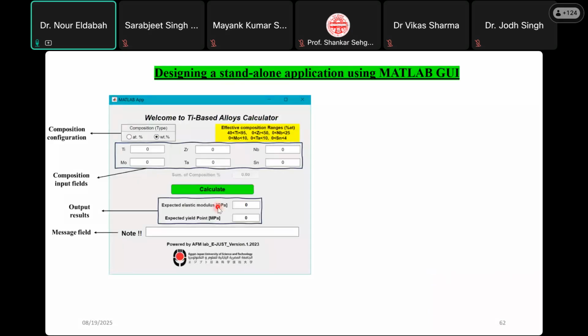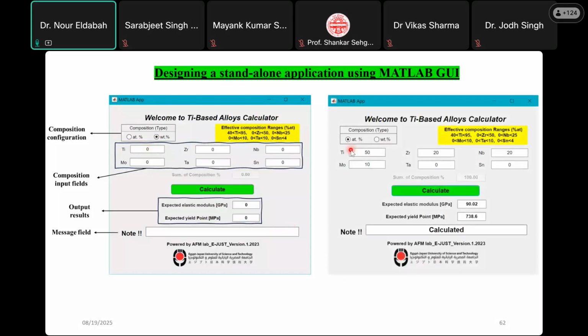Finally, to make our work effectively working, or accessible for all users, you can take your code and make a standalone application. In this standalone application, you can feed in your chemical composition, and it can calculate for you the expected elastic modulus and expected yield point. Actually, I built this application after the first case study, and it was very beneficial for me. You can imagine that in my lab at Egypt-Japan University of Science and Technology, it takes around 1 week for production and processing of the alloy, and at least 1 month for testing. If you are dealing with around 5 compositions, you will take at least 3 to 4 months to get your results and start to analyze them.